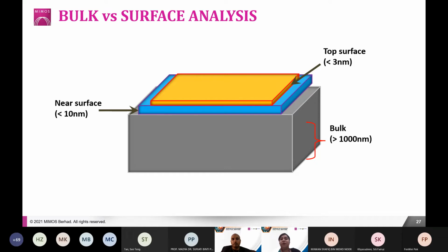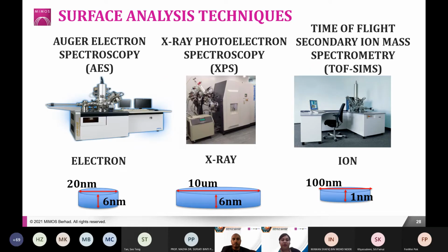You can't use the normal EDS because if you're using the bulk analysis, you will get the whole region. You're not only getting the top near surface. All right. So this is where we have different kinds of probe size. For example, under Auger electron spectroscopy, the AES, the source is electron. So the probe size is about 20 nanometer and the depth of the penetration is about 6 nanometer. So you can get information up to 6 nanometer.